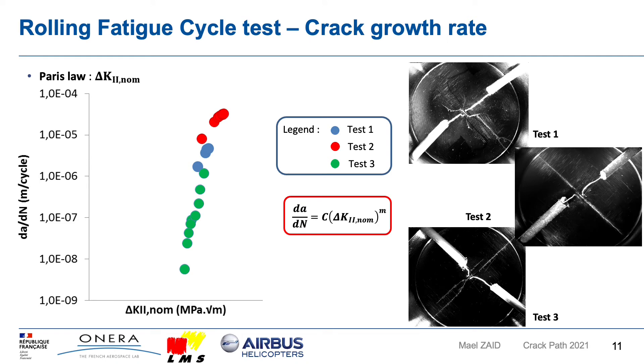For each test, this kinetic law is obtained. If you look at each test independently, we get different Paris slopes — one for each test. This can be explained by the fact that the nominal stress intensity factors do not take into account physical phenomena like friction, wear, debris, or oxidation that can occur between the crack lips when loaded in shear mode plus compression. These interactions between the crack lips make understanding of the crack path complex because they decrease the range of the stress intensity factor in mode 2 due to friction or asperities along crack faces, which oppose the displacements of crack flanks.